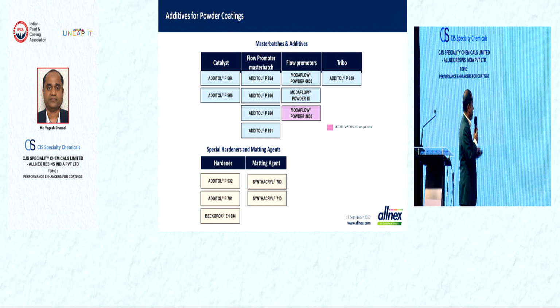So just to give you an overview of the chemistries, this Additol P964 is recommended for the conventional type of powder coating. It accelerates the rate of reaction. Then Additol P966 is a catalyst with 15% active substance dispersed in super durable polyesters. So that's why it is recommended for the super durable type of polyester coatings.